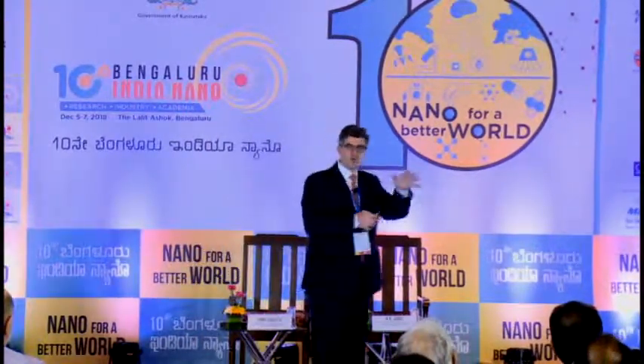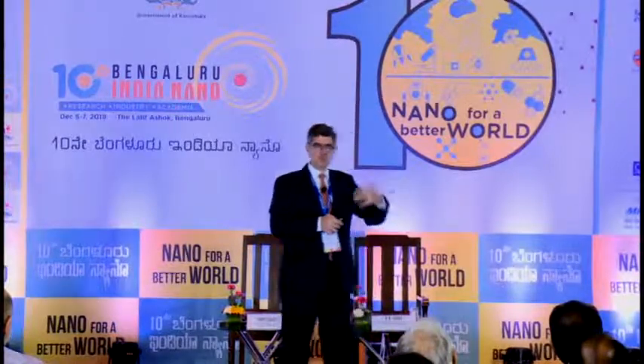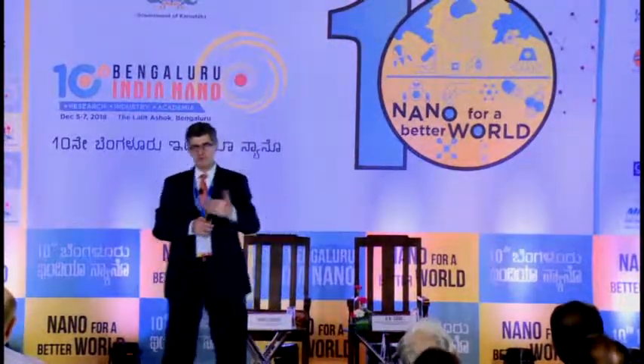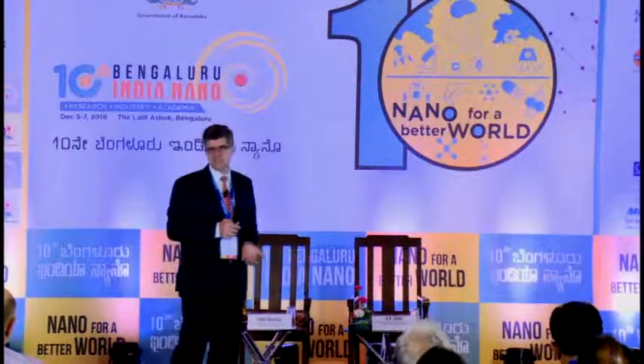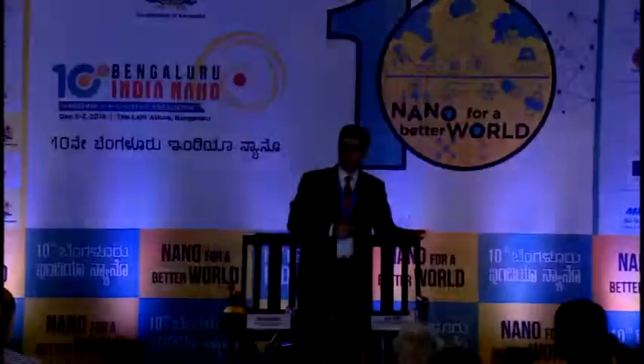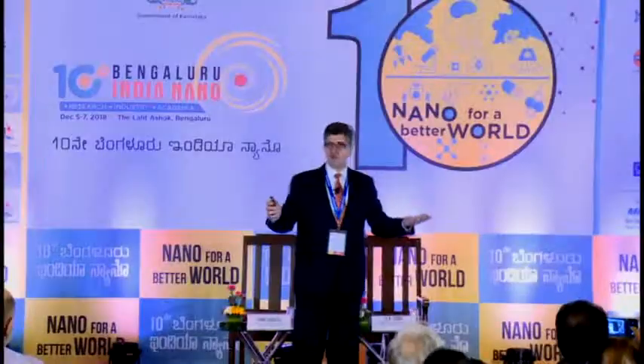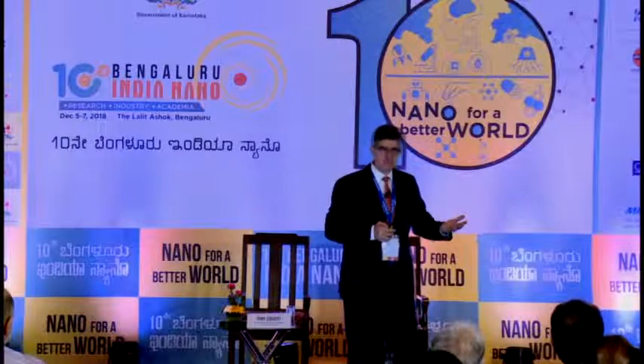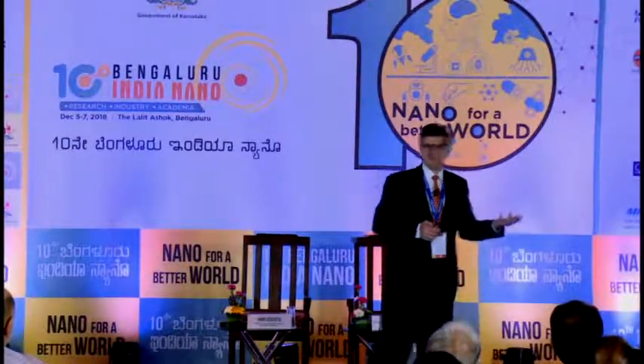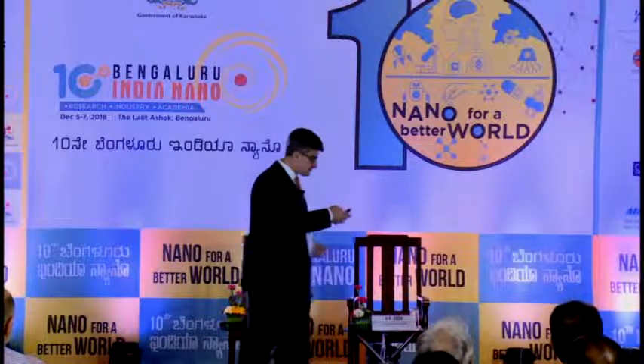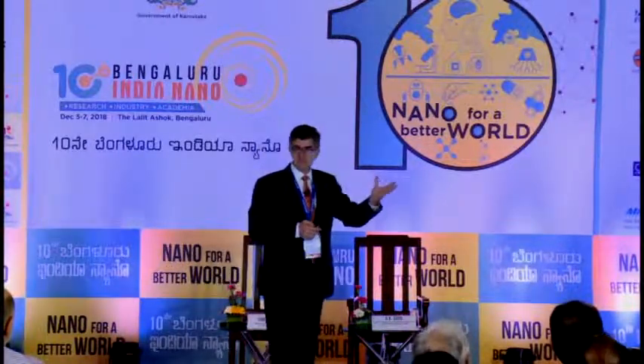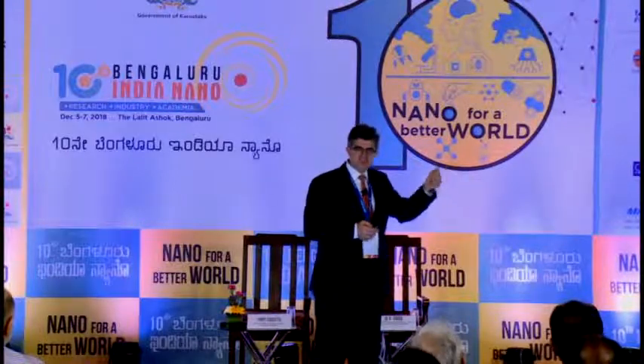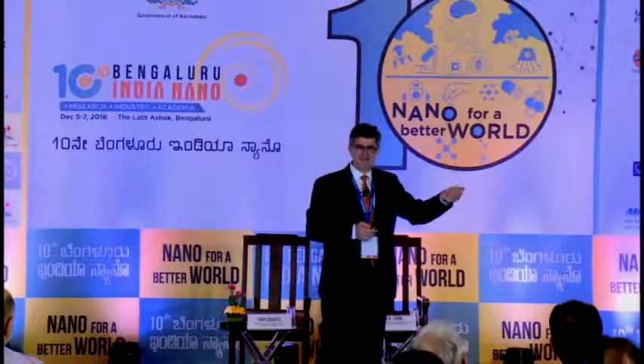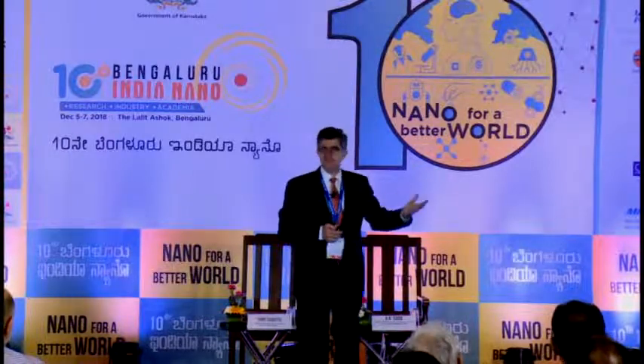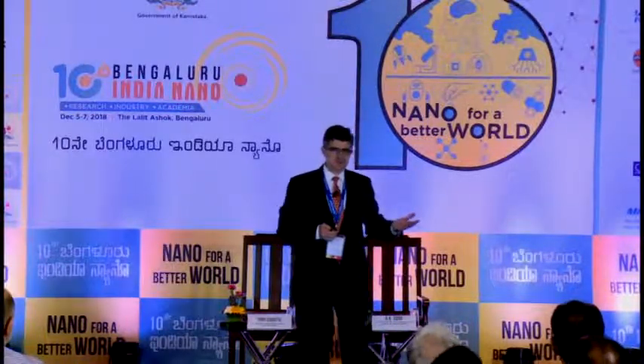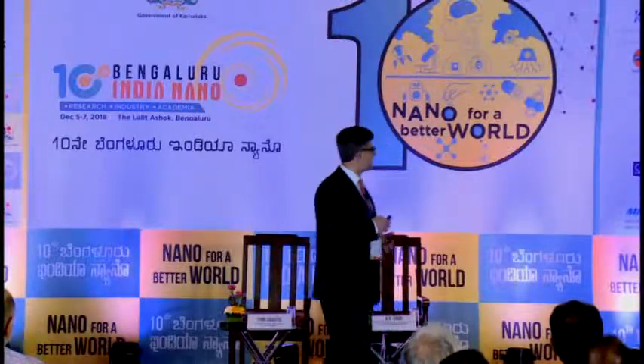And depending on how flakes are ordered in the film, conductivity will be from 1,000 to typically 10,000. If we do spin coating or vacuum annealing, we can currently get about 16,000 siemens per centimeter, which is a very, very high conductivity. Compared, for example, to activated carbon we use in supercapacitors, which we consider to be a conducting electrode, it's about 3 orders of magnitude higher than that here. And again, we produce it by buying for $20 a spray gun for spraying paint in a hardware store, Home Depot, in the US, and do it here. So again, it's possible to do nanotechnology with simple means here.